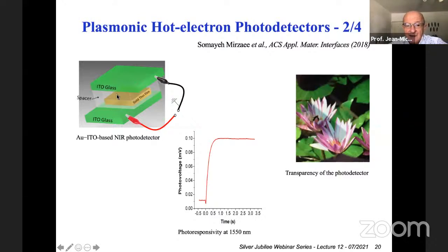And we fabricate an air capacitor with a spacer of 30 microns, typically 20, 30 microns. And with that spacer, which is a spacer used when people design dye-sensitized solar cells, we fabricate this capacitor, and that is the response of the capacitor. Of course, the light is chopped in front for the capacitor to respond. And this is the response of the capacitor demodulated at the frequency of the chopper, in millivolts, when we send the light. Okay, so we have a photodetector made with these materials.